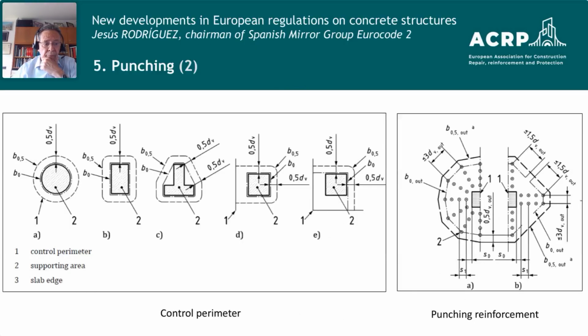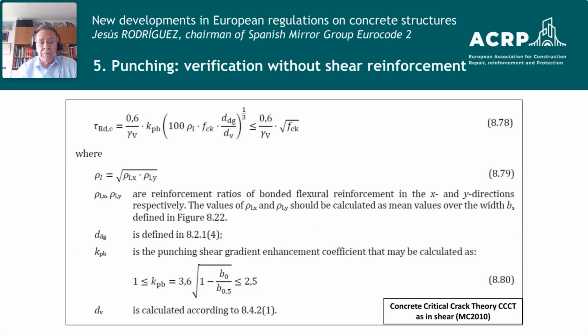So we have to verify the typical punching perimeter. In this case, it has been established at a distance of 0.5 times the effective depth from the columns, and then of course we are also obliged to verify the external perimeters in order to define the extension of the reinforcement. So as in shear, we have the critical crack theory, and we have a very similar expression for the shear stress resistance, the shear strength of the concrete when there is no punching reinforcement, where, as always, the ratio of reinforcement needs to be taken into consideration, always the rate of reinforcement in both directions of the slab.